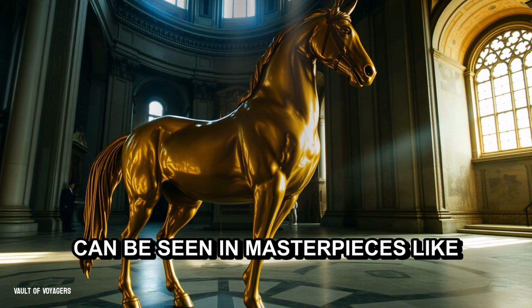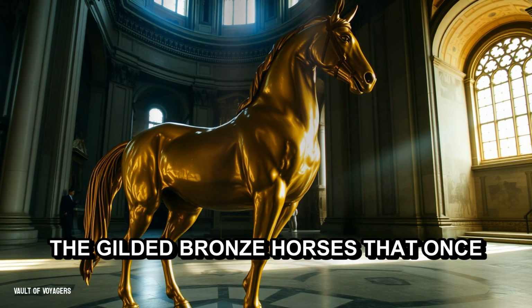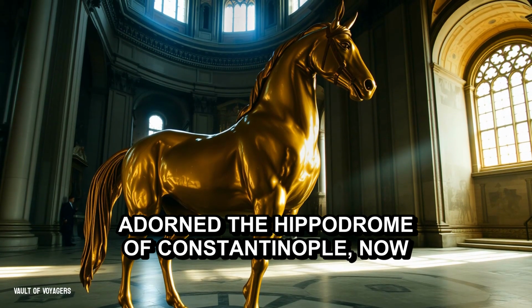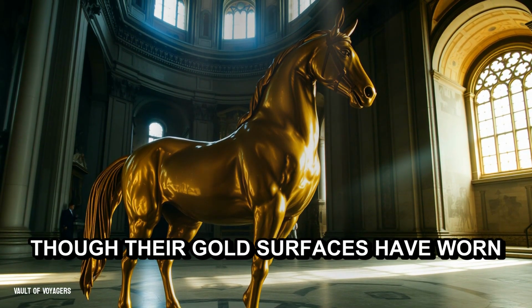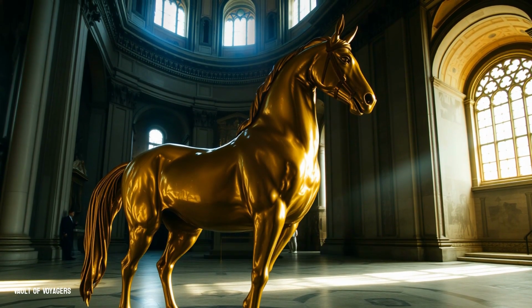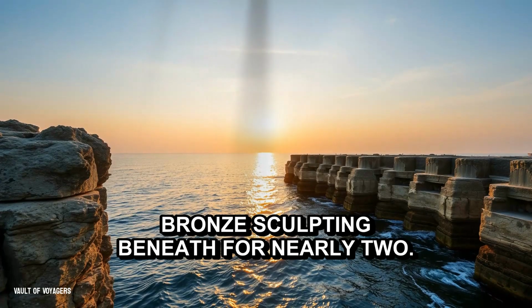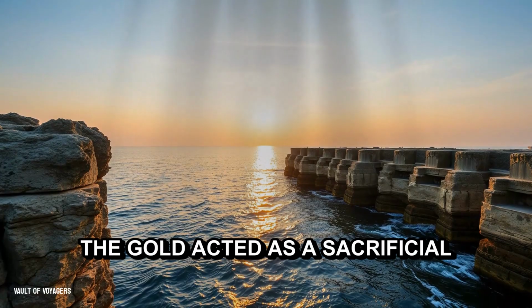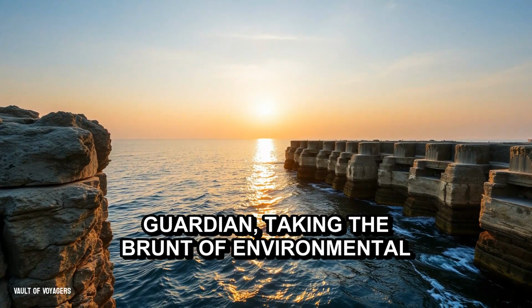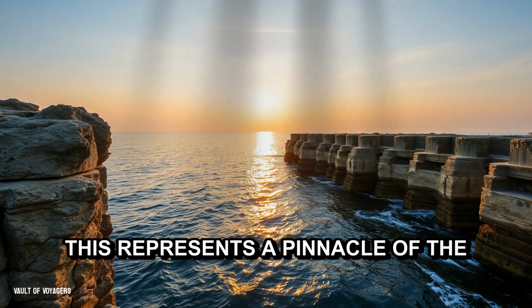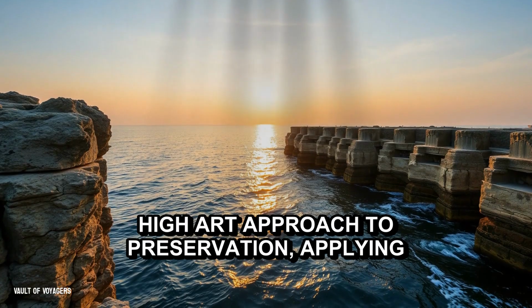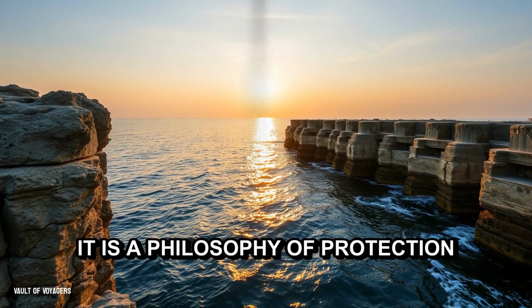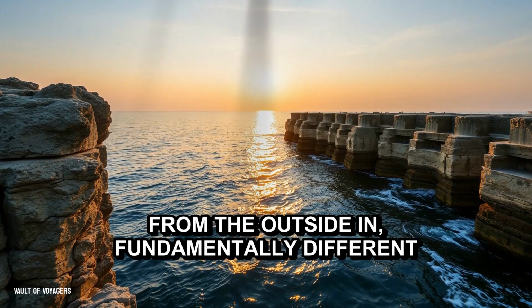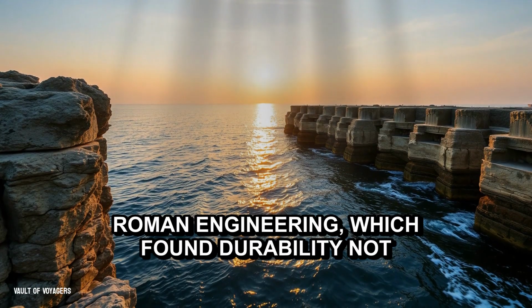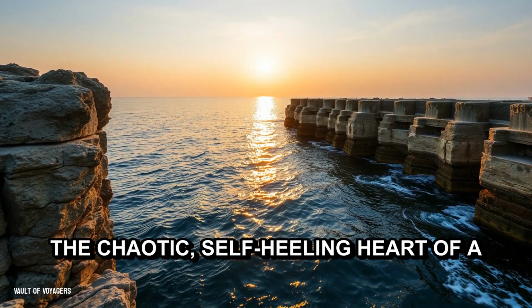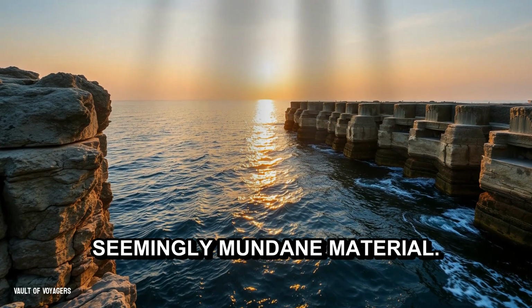The legacy of this perilous art can be seen in masterpieces like the gilded bronze horses that once adorned the Hippodrome of Constantinople, now housed in St. Mark's Basilica in Venice. Though their gold surfaces have worn away in places over the centuries, the technique helped preserve the exquisite bronze sculpting beneath for nearly two millennia. The gold acted as a sacrificial guardian, taking the brunt of environmental exposure so the art could survive. This represents a pinnacle of the high art approach to preservation, applying a precious, impervious skin. It is a philosophy of protection from the outside in, fundamentally different from the next great secret of Roman engineering, which found durability not in a precious coating, but in the chaotic, self-healing heart of a seemingly mundane material.